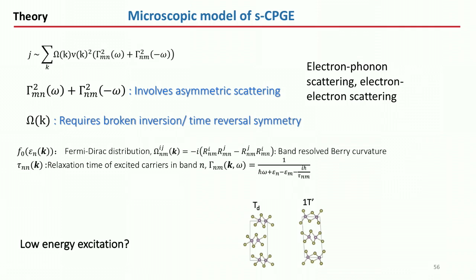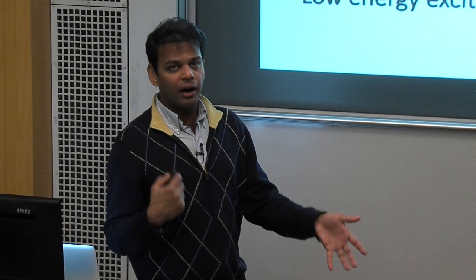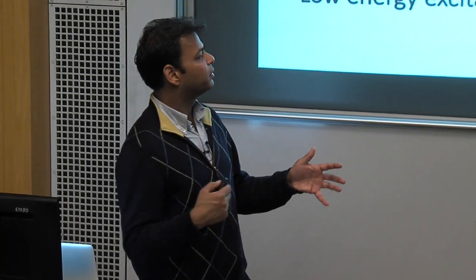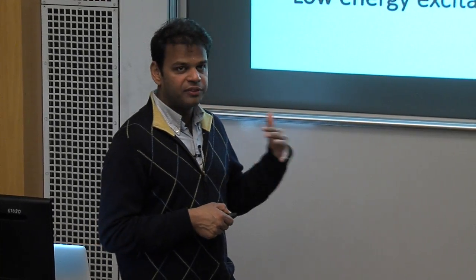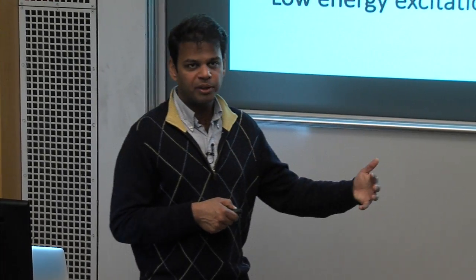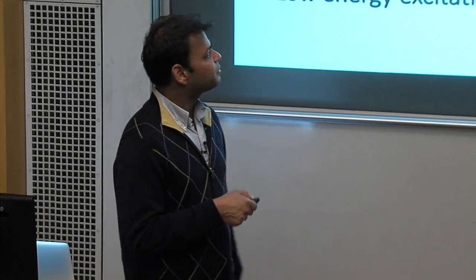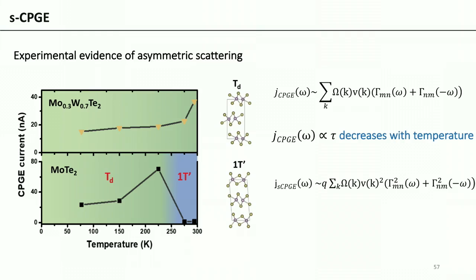But another very important aspect that we learned was, unlike any other spectroscopic technique, one of the requirements for this inhomogeneous excitation-based CPG, which we call spatially dependent CPG, SCPG, is that the response will be non-zero only if the scattering or relaxation of the carriers is asymmetric, which basically means scattering at plus K and minus K has to have different rates. If this is not satisfied, then the response will be zero. So this basically means we have developed a new technique to probe very different aspects of microscopic physics of this system.